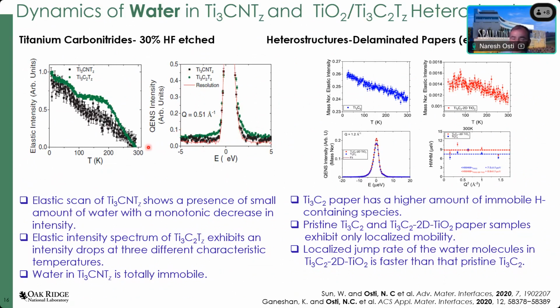Now what we have done so far is that we looked at the mobility of the water in MXene powder. Now we move our attention to the dynamics of the water in MXene paper. MXene paper means that once you have the MXene layers, you can delaminate the MXene and get a sheet-like structure, and then we look into the water dynamics in that MXene paper and compare it with that of the MXene heterostructure. We had the MXene heterostructure, that means MXene in heterostructure with titanium oxide.